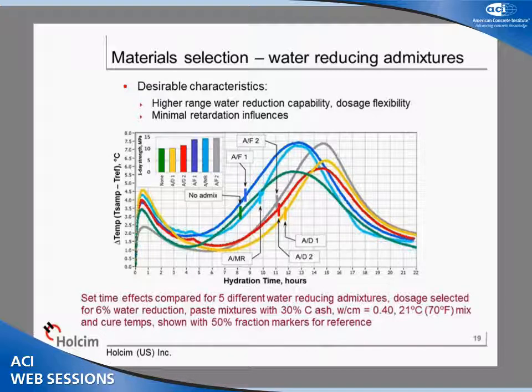These are some comparisons of different admixtures selected for dosage rate based on about the same level of water reduction that you could accomplish. And it's no surprise that the common type AD products have a lot of associated retardation. Not a good selection for highly sustainable mixtures in most cases because retardation becomes one of our problems. But even the polycarboxylates and mid-range type products have some variability in set time influences, and to select one with the minimum amount of retardation that's associated with it is probably something that we want to do.